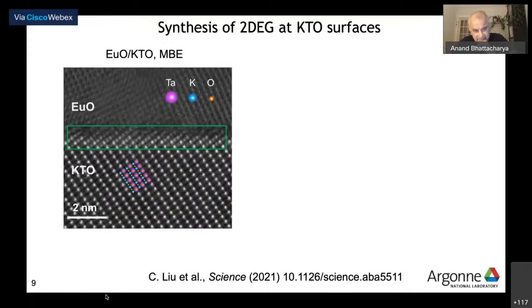So how do we make our samples? We did this in a couple of different ways. We grew EuO on KTO 111 using MBE. And in fact, we made no effort to try and make it very crystalline. It turns out europium does not want to stick to potassium tantalate at the temperatures that we were growing our samples. So there are various different things we did to make this happen. And eventually we grew a layer of EuO on KTO. I should really say EuX because we don't know the composition exactly.